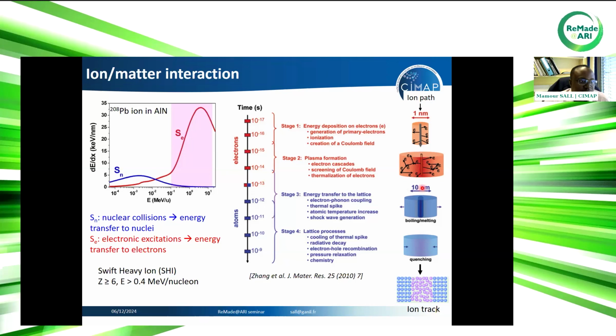So what happens generally is the energy transfer is high enough for melting the material locally. So here, for example, we have a melted part of the material, and this melted region is surrounded by a very cold region, let's say at room temperature. So we will have a quenching of this melted part, and this will result in what we call an ion track. An ion track is a modification of the structure of the material along the ion trajectory. This is one of the characteristic defects we can have with swift heavy ion radiation. Of course, this is not the only one, but this is the defect we look at more often, let's say. But we can also have less complex defects like point defects.